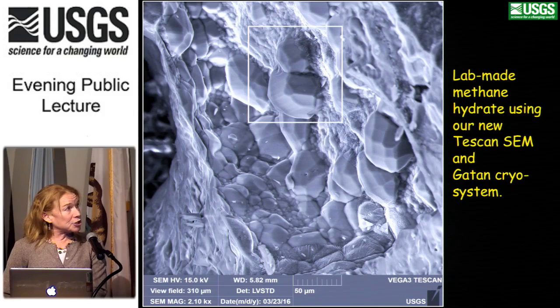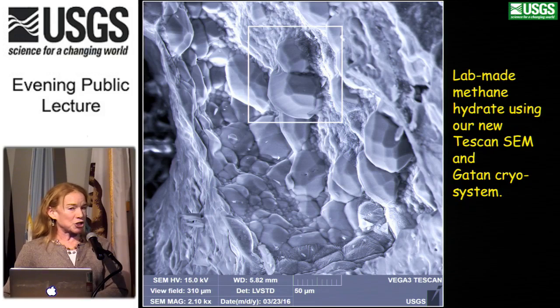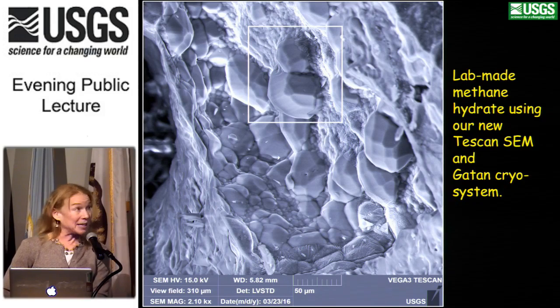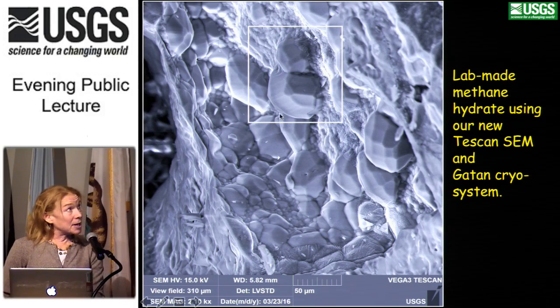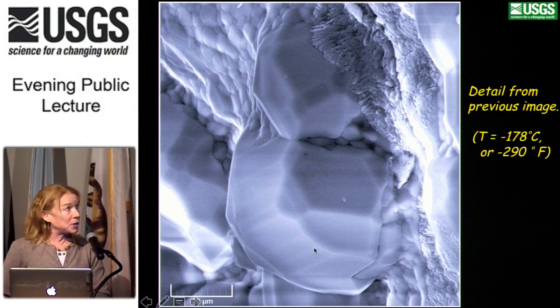And these final two images of methane hydrate are with our newer TESCAN SEM here on campus. We have a low vacuum capability. We can actually keep a pressure within the chamber. So now I can look at samples for more like an hour and a half instead of 10 minutes before they change rapidly. This box here, I'm going to enlarge in the next picture, and there's just two big, beautiful methane hydrate crystals here.